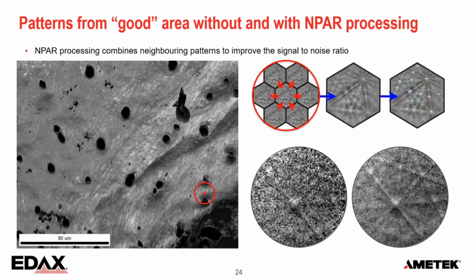The NPAR thing is nice because it's something we do offline. It costs a little bit in lateral resolution. In most cases, that doesn't hurt too much, but it does not add to the electron dose that we have to apply to the sample. Now, this example is from the good area. So this is one of the better patterns.